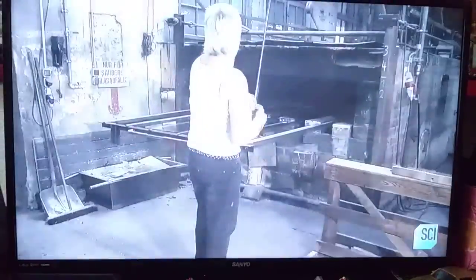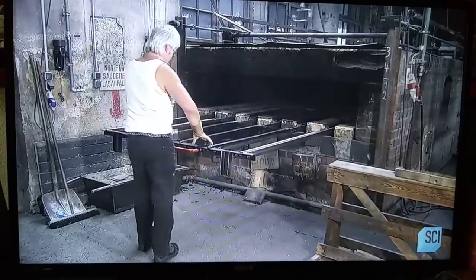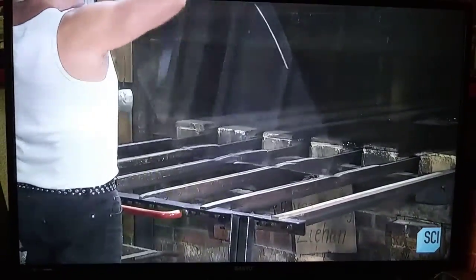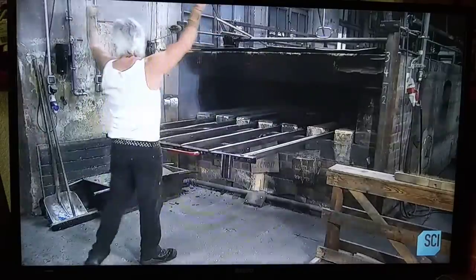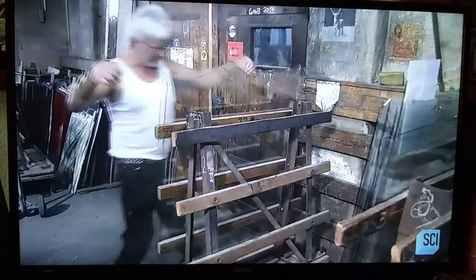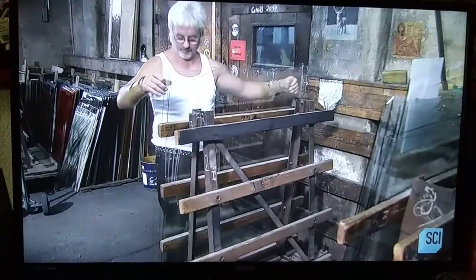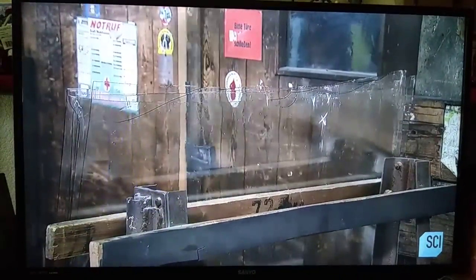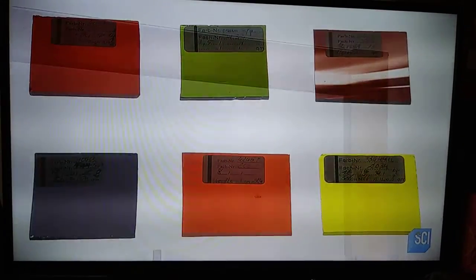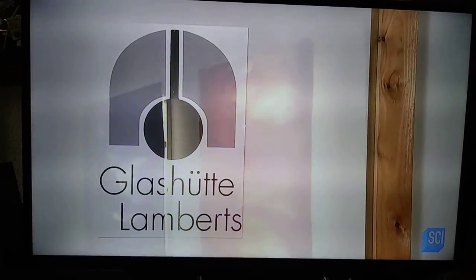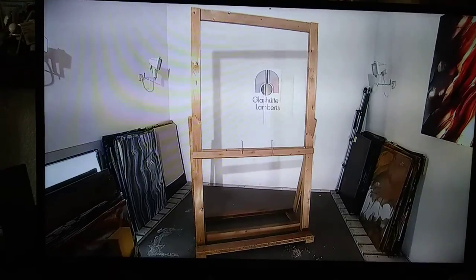The flat sheet goes into the annealing oven for a gradual controlled cool down. This relieves stress and prevents cracking. The flattening master's assistant removes the glass from the annealing oven and performs a visual inspection. The last step is to cut the edges straight. To make multicolored and textured glass, they add additional ingredients during the melting process. Mouth-blown window glass contains natural variations that play with the light and create a subtle glow. A glow that machine-made window glass can't replicate.